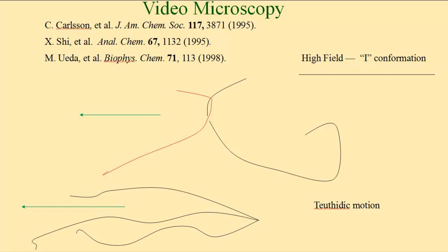if you had the situation seen here, the electric field would drag out the long end of the red chain and pull the other end of the red chain backwards until it unentangled itself from the invisible-in-microscopy black chain. The motion, therefore, is motion in which the chain ends move first and the chain center follows.